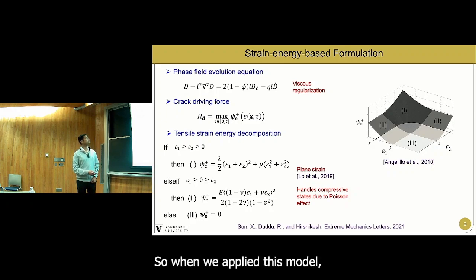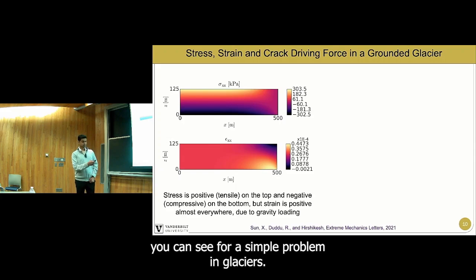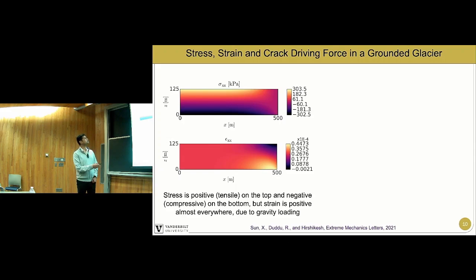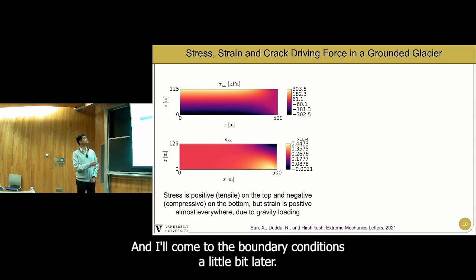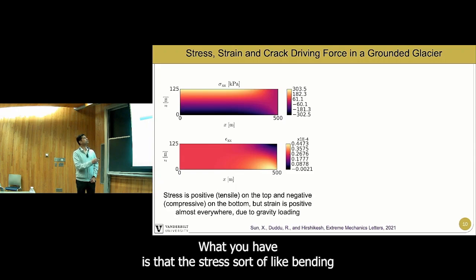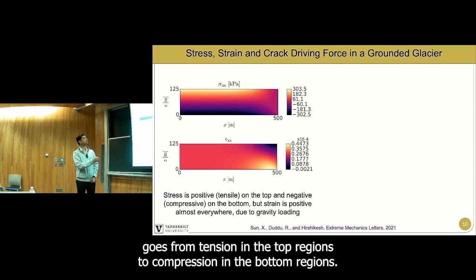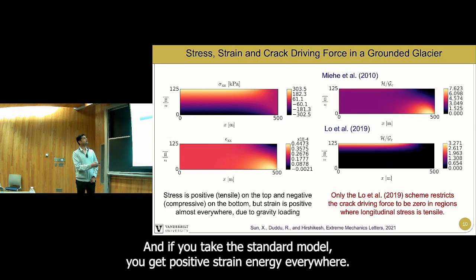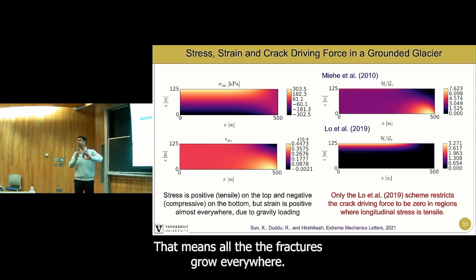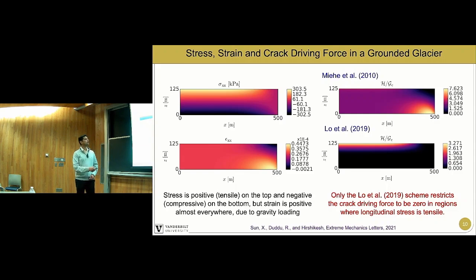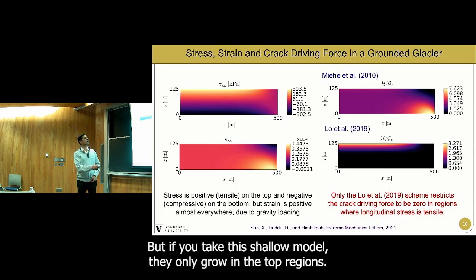So when we apply this model, you can see for a simple problem in glaciers, and I'll come to the boundary conditions a little bit later, what you have is that the stress, sort of like bending, goes from tension in the top regions to compression in the bottom regions. And if you take the standard Miehe model, you get positive strain energy everywhere. That means all the fractures grow everywhere. But if you take this Yu-Sheng-Lo model, they only grow in the top regions.